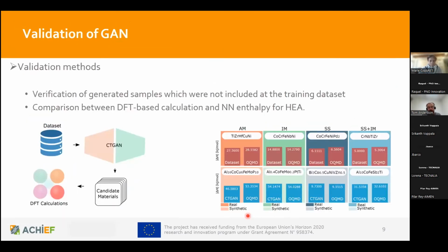And as a validation method for these alloys that the generator generated, data sets and material databases are used. So basically first, this data set that has been generated has been compared with this materials database that has been found, to see that the phase used in the data set corresponds with the materials database that will be used to validate the neural network candidates. And then finally, these neural network candidates are compared against the materials database found from open sources. And for that, it seems to be quite well predicting the phase for these different alloys.